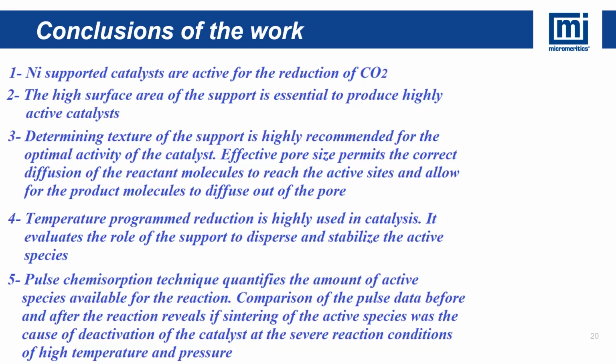Conclusion of the work. The first thing is that we conclude that nickel-supported catalysts are active for the reduction of CO2, therefore good active catalysts for the Sabatier reaction. The high surface area support, as we have seen, is essential to produce highly active catalysts. We could see that the high surface area material has much higher activity for CO2 than the lower surface area material.